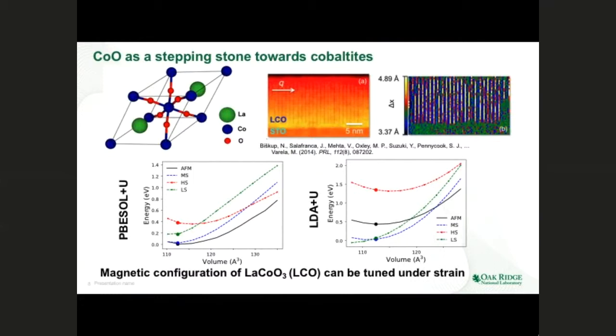And when people try to simulate this, not even this epitaxial case, but just the bulk lanthanum cobaltite, depending on the DFT functional that you use, you're basically getting different ground state magnetic structures. For example, with PBEsol plus U, and U is equal to 4 in here, you're getting more like an antiferromagnetic ground state. But with an LDA plus U, you're getting more like a mixed spin or a low spin state as the ground state in here.